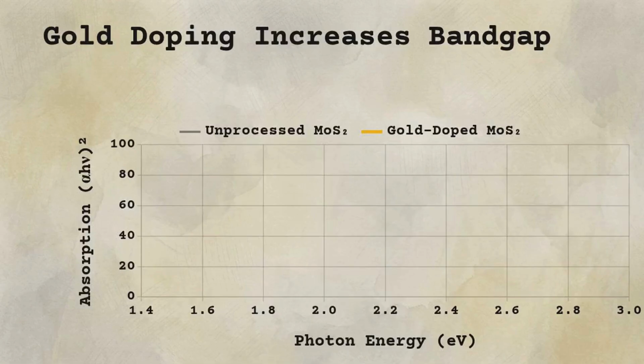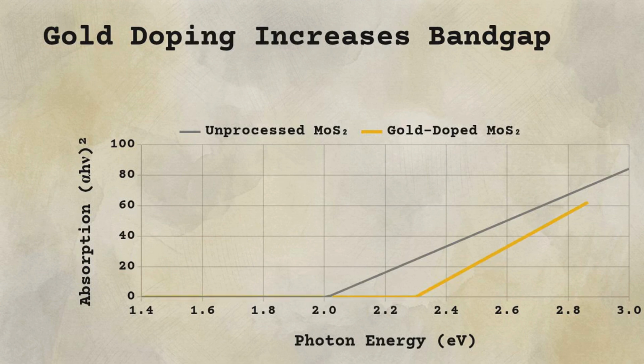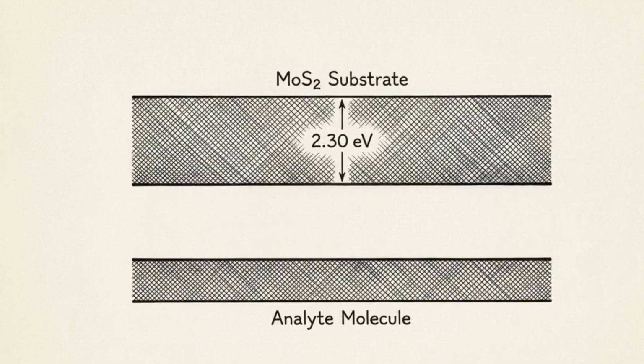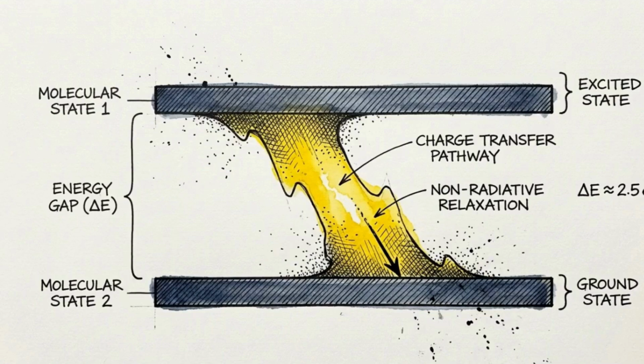Here we see a Tauc plot, which translates the UV-vis absorption data to reveal the bandgap energy. The plot displays two distinct lines, the unprocessed MoS2 base and the new, laser-processed, gold-doped substrate. Evaluating the x-intercepts shows a clear shift. The bandgap energy increases from 2.01 electron volts in the raw state to 2.30 electron volts after the gold doping. This higher 2.30 electron volt bandgap aligns the energy levels of the substrate more closely with the molecular orbitals of foreign analytes, establishing a highly efficient bridge for charge transfer.